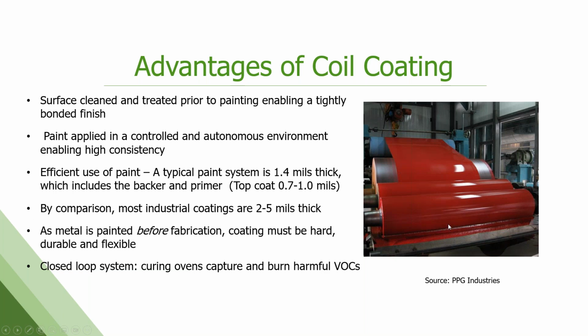These are solvent-based paints, but we use closed loop systems on these lines. So the ovens are burning those solvents off to cure the paint. Those solvents are captured, oxidized through an RTO. The heat generated from that is pumped back into the ovens to fuel the ovens. So all the VOCs are being captured, and the final product is VOC free at the end of the line.